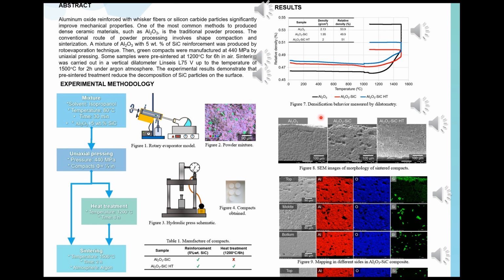As shown in Figure 8, microstructural analysis reveals that sintered composites present a decomposition of silicon carbide reinforcement particles on their surface, leaving macro pores in the material. This is observed in the mapping on the aluminum oxide silicon carbide sample in Figure 9.